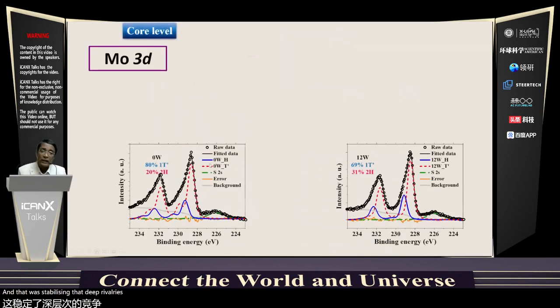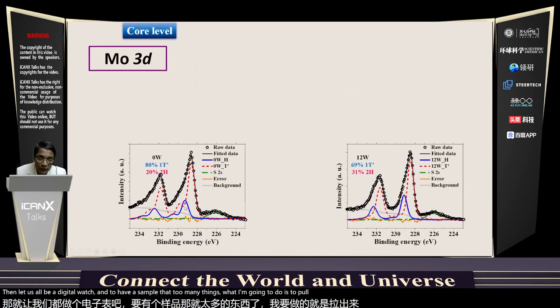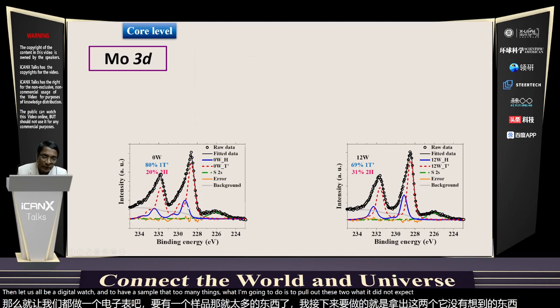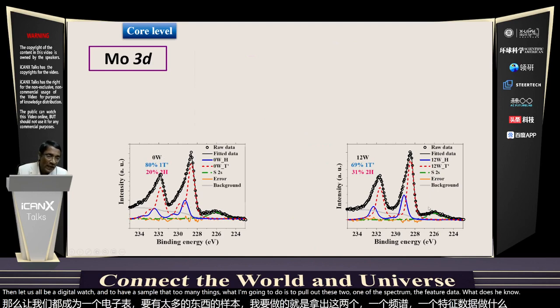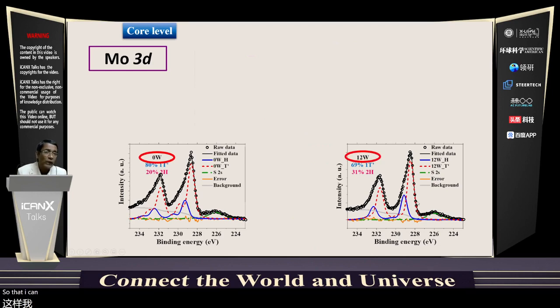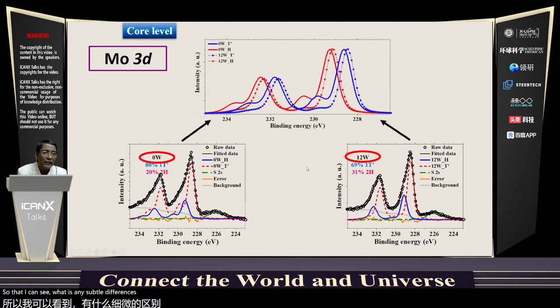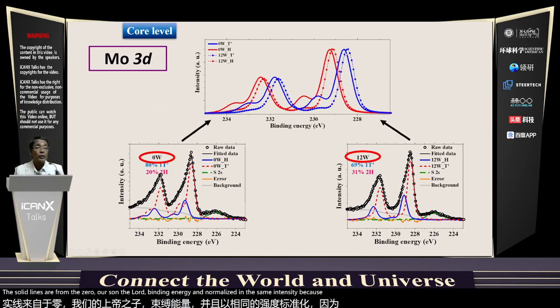Then let us compare the 0 watt and the 12 watt sample. There are too many things. What I'm going to do is pull out these two molybdenum spectra, the fitted data of the 0 watt and the 12 watt, and compare them together so that I can see any subtle difference. And that is what is being done here. The solid lines are from the 0 watt sample. The lower binding energy I've normalized to the same intensity because I want you to focus on the energetics now.